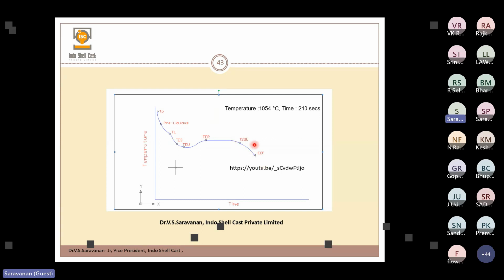So sometimes it will deteriorate the metal, because these low melting alloys will solidify late, and then they go towards the grain boundaries and settle there in carbide form, maybe vanadium carbide, chromium carbide, titanium carbide, whatever it may be. The amount may be very small, but it settles as metal carbide. So then the grain boundary will become very weak.